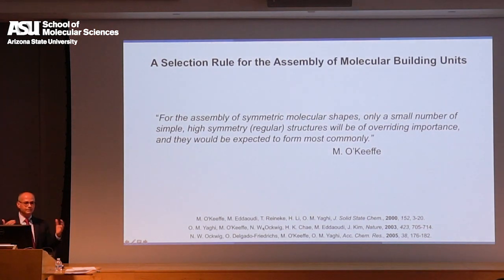So how do you choose from among the millions and millions of possible structures, almost infinite number of possible structures? And Mike said, for the assembly of symmetric molecular shapes, only a small number of simple high symmetry structures will be of overriding importance, and they will be expected to form most commonly. Okay, so as long as you're starting with symmetric units, you're very likely to fall into the most symmetric net. So that made life much easier for Mike to basically say, hey, if I want to know what the synthesis is gonna produce, I have to go after the most symmetric structures. And those turn out to be not many. It could be 50 or so for different geometries. And most of the time, he was correct. Sometimes he was not correct. We made things that were not as symmetric as he thought, but most of the time it was correct.